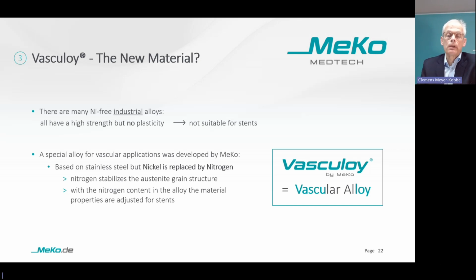Nitrogen takes over the responsibility of nickel. So nitrogen stabilizes the austenite grain structure of the alloy. And austenite grain is non-magnetic and corrosion resistant, two properties we need for stents. Nitrogen has also a strong effect on the mechanical properties of an alloy. The higher the nitrogen content, the higher the strength, but also the brittleness, which we don't want in stents.